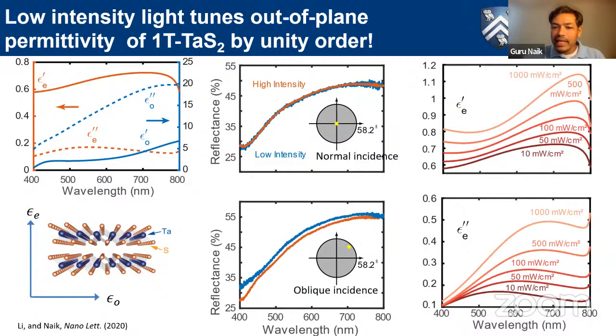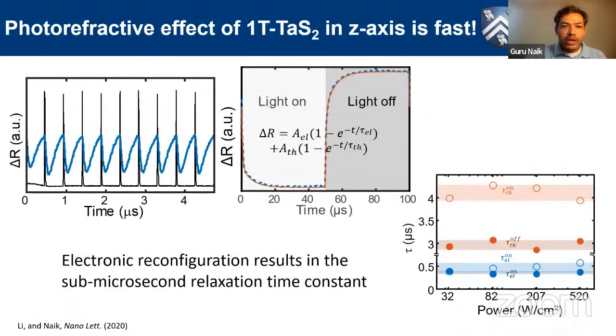So we basically extract this out of plane permittivity as a function of illumination intensity. Here we have the illumination intensity, all incoherent white light illumination, from 10 milliwatt per centimeter squared to 1000. And just to give you an idea, 100 milliwatt per centimeter squared is one sun intensity. So that's ambient sunlight, right? So we are talking about simply ambient light changing optical constants by this much. Which was quite exciting, interesting. And we wanted to find out why this happens, how fast it happens, all those things.